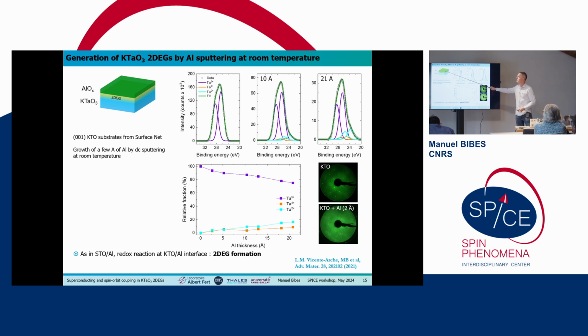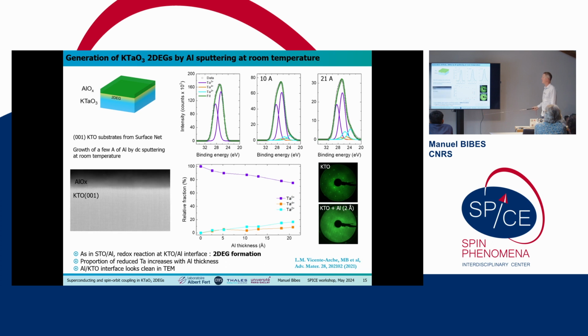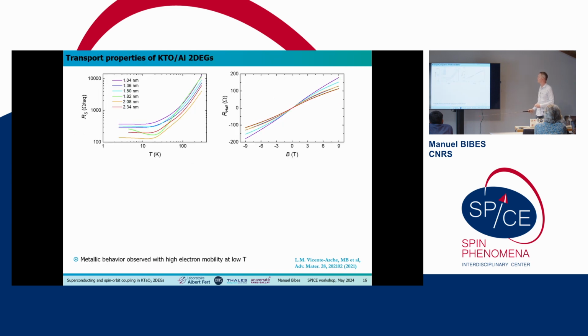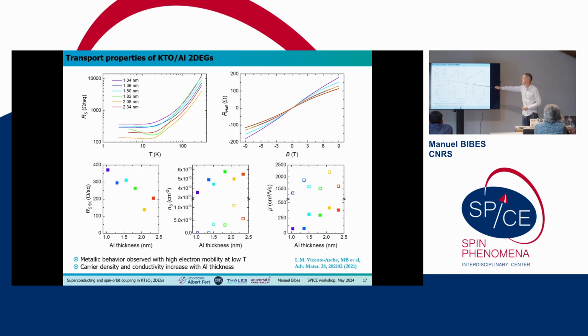At the same time, the aluminum is oxidized, and so we have an insulating layer of aluminum oxide. And because of the reduction of the tantalum, we create oxygen vacancies. They create electrons. We have a 2DEG. And we can check the interfaces between the two materials, which looks pretty nice. And from the transport, we see a metallic behavior, which is tunable by the thickness of aluminum that we grow. You see that the resistance decreases. The more aluminum we put, the more carriers we have, and the resistance decreases. Okay, so that's quite an easy way to generate a 2DEG because we do all this at room temperature in the sputtering.